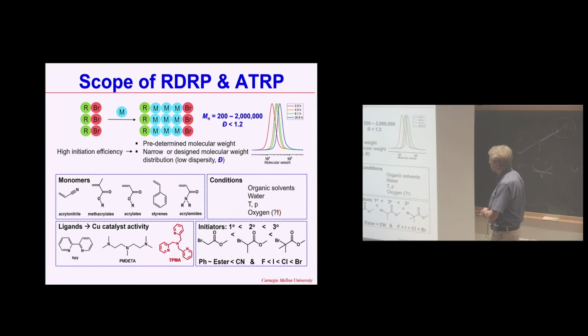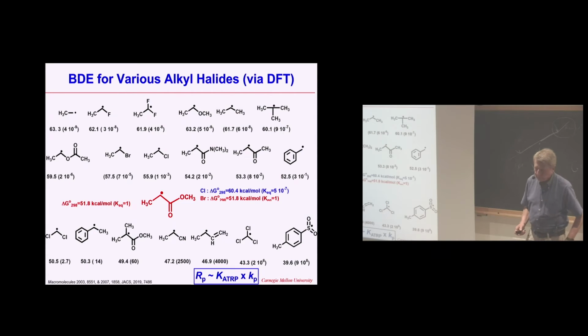Typically we would use organic solvents, sometimes water, as I mentioned, variable temperature, pressures, and I will show you also that we can tolerate oxygen, which is normally extremely challenging for any radical polymerization. We typically select initiators which would mimic dormant chain ends. So this would be secondary bromopropionate for acrylates. This would be isobutyrate for the methacrylates, and I will show you some examples of how different reactivities they have. And then I will show you also some examples of these catalysts or ligands which are used.